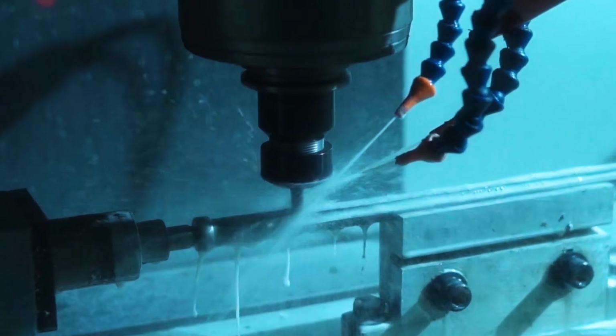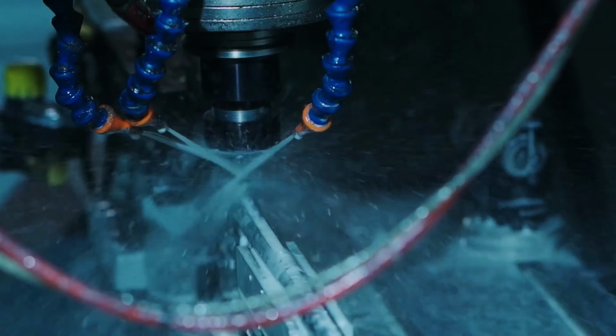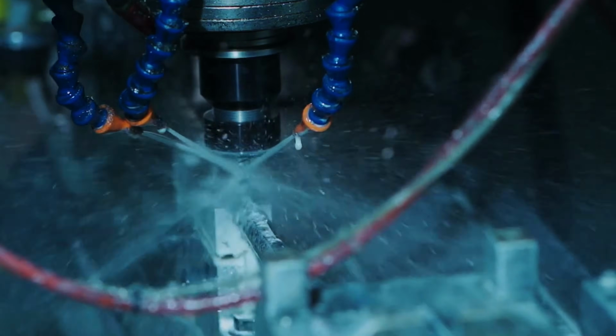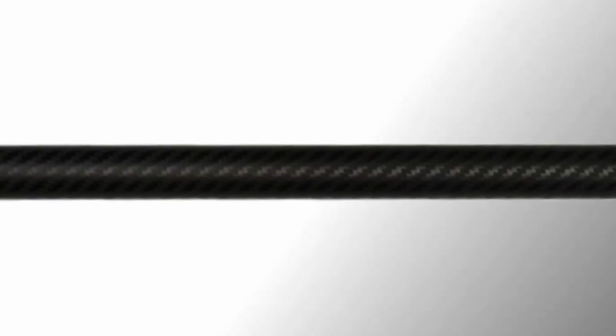So here's how the barrels actually work. They start with a 416R stainless steel liner that handles all of the pressure and the rifling and the chambering, you know, all of the critical parts that the barrel needs to do. And then the barrel gets wrapped in a high-strength aerospace-grade carbon fiber using some sort of proprietary process that I can't adequately explain here in a YouTube video. And what you end up with is often a 60 to 65% lighter barrel compared to a full steel barrel like the ones that are here on the table. This makes your rifle lighter for hunting or competition or doing long-range movements with the rifle, and that's one of the big wins to it.